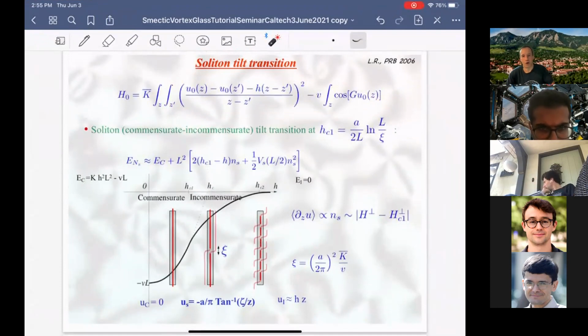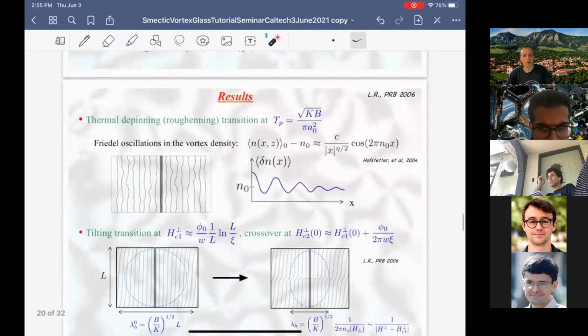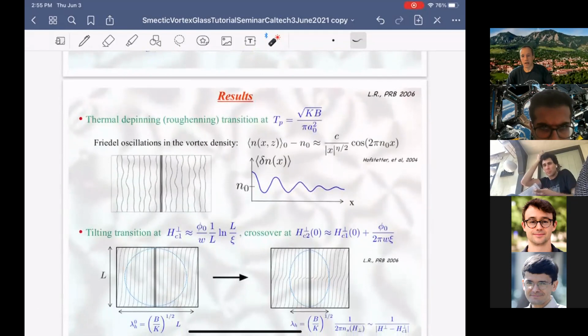It's the vortex analog, where I integrated the modes away from the impurity. But I could reconstruct those modes now because I know the whole distortion, because the bulk modes are related to the surface modes on the columnar defect. If you reconstruct it, it looks like this. So this is sort of the Meissner phase to the tilting solitons of Peierls and Nabarro. And when you exceed the HC1 in the transverse direction, you develop a single soliton. But of course, that soliton is not just a single soliton, it propagates into the bulk. It decays with an amplitude, but nevertheless, it distorts things very far away, out to the length scale of the system size inside this bubble. So that's kind of a cool problem.